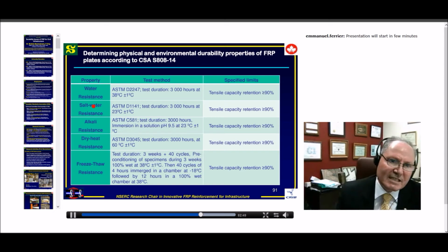We have the water resistance, salt water resistance, alkali resistance, dry heat resistance, and freeze-thaw resistance. And here you have all the duration, the standard test method, and the specified limit. It's mainly tensile capacity retention, as you have it here, greater or equal to 90%. This is for the Canadian.